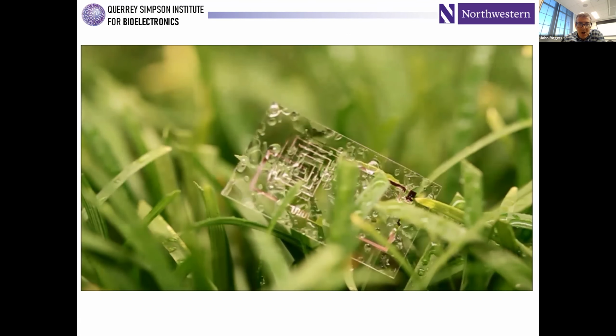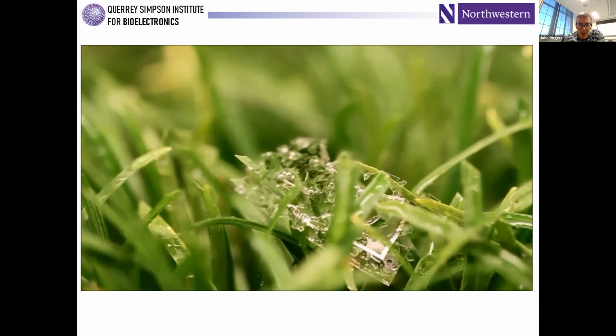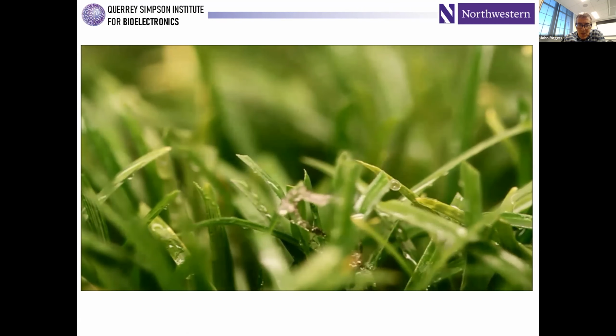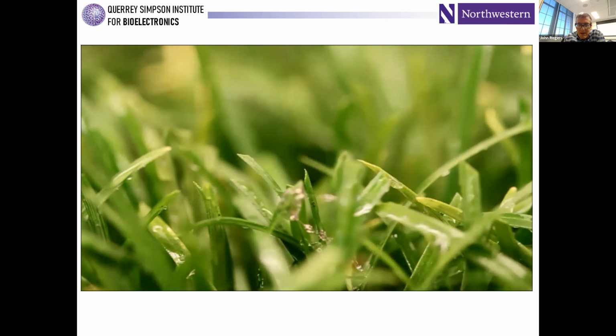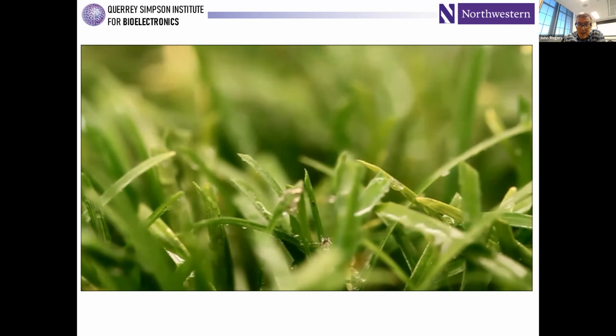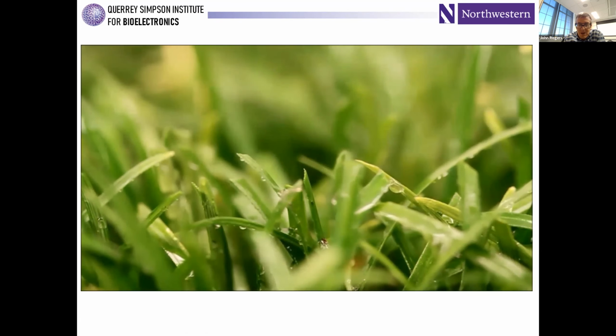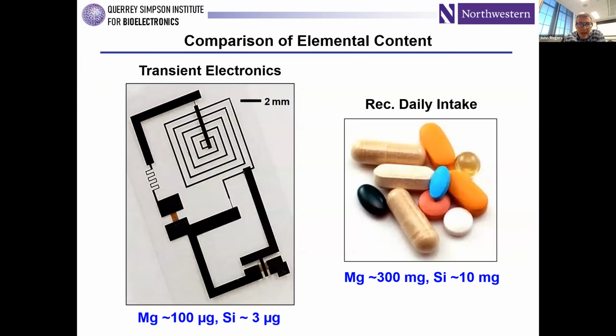This is something we did for DARPA in the very early days, just showing how these circuits can melt away with kinetics that are really defined in this case by the crystallinity of the silk fibroin that we're using for the substrate. It dissolves very quickly, and then the individual components of the different devices dissolve over slightly longer timescales. Anyway, you can do that.